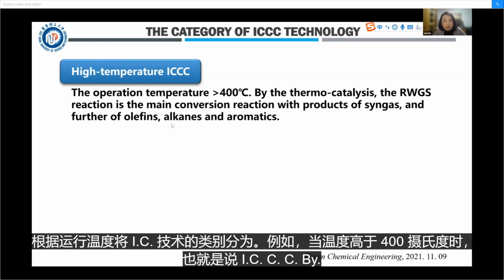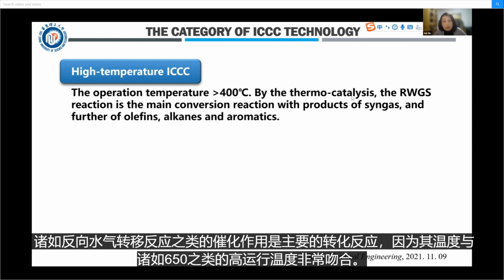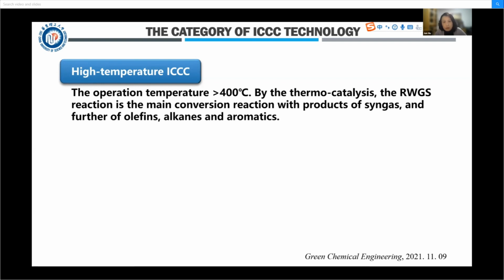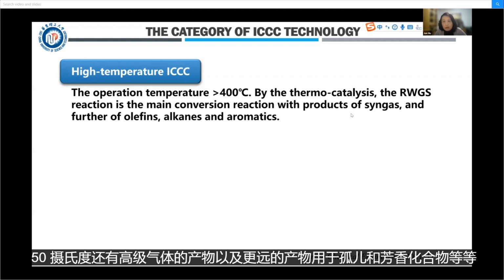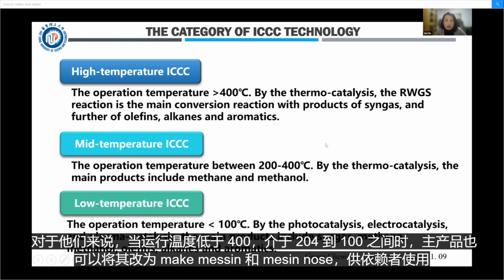When the temperature is higher than 400 degrees C, that means high temperature ICCC. By thermal catalysis, the reverse water gas shift reaction is the main conversion reaction because its temperature matches the high operation temperature, such as 650 degrees C, with products of syngas, and further olefins and aromatics and so on. When the operation temperature is between 200 and 400, the main products change into methane and methanol, depending on the different pressures.